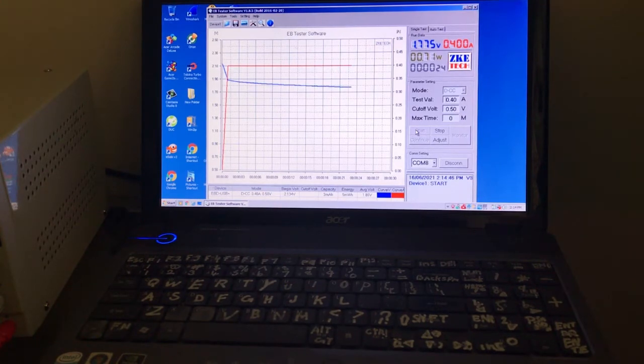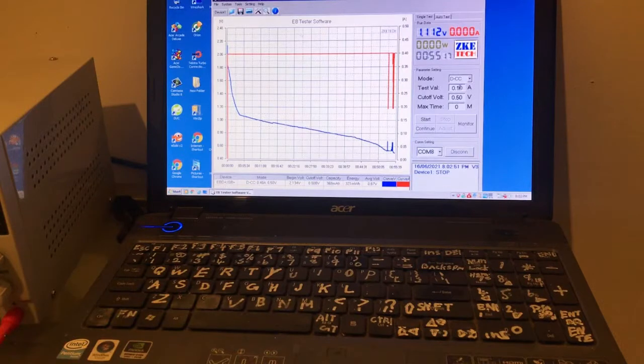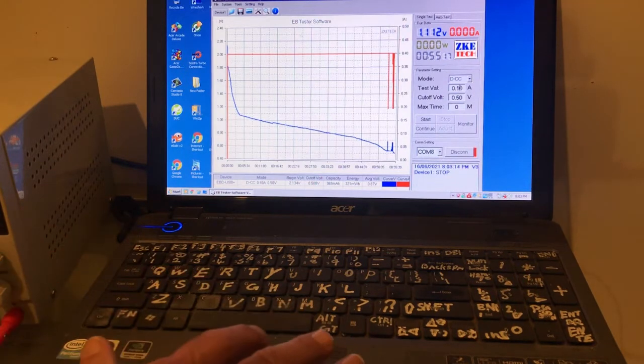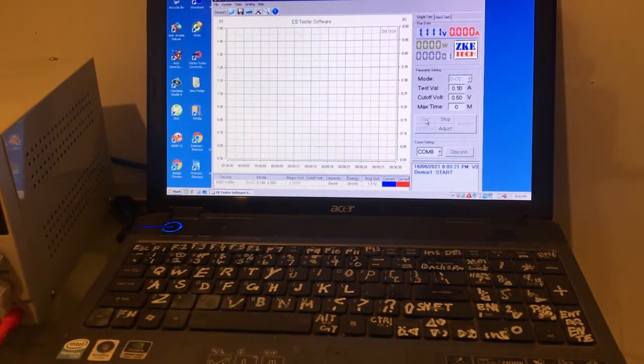Alright, back. 55 minutes on that run with 400 milliamps as the load. Average voltage has gone down to 0.87, 368 milliamp hours and 321 milliwatt hours. So 400 is probably a bit too heavy. And checking to see if there's anything left, which I think there might be, with 100 milliamps.